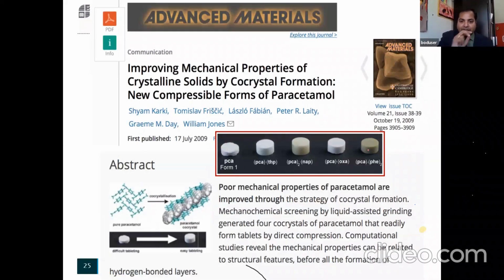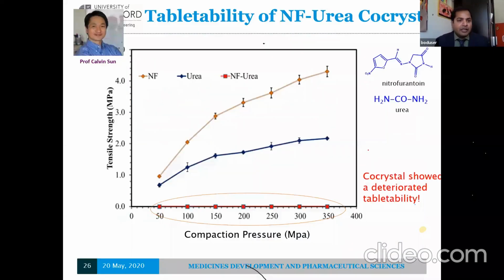Having said this, what we have experienced was that Professor Calvin Sun from the University of Minnesota has helped us with these studies. We have undertaken 5 or 6 co-crystal studies for mechanical properties, but as a representative example for you, I posted here nitrofurantoin with urea. What happened was, if you look at these profiles against the tensile strength, when you apply the pressure, what happens to the crystalline materials?